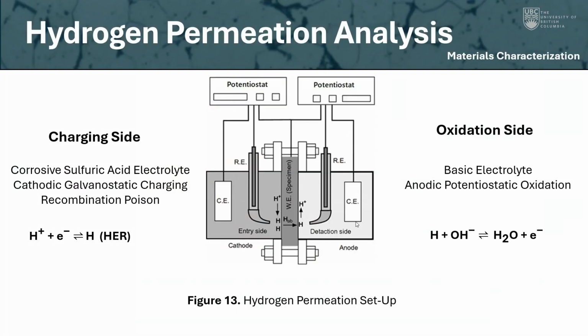And then the final step to our materials characterization is running hydrogen permeation tests. So we want to see, based on the microstructure, how susceptible the steel is to hydrogen penetration. So this tells us, again, the intensity of hydrogen trapping based on microstructure and inclusion. This is just one of the corrosion or electrochemical techniques where we have our steel membrane in the center. On the left side, we're essentially generating hydrogen by applying a negative potential to drive the hydrogen evolution reaction.